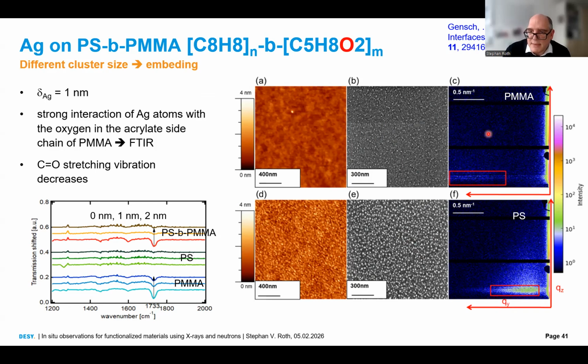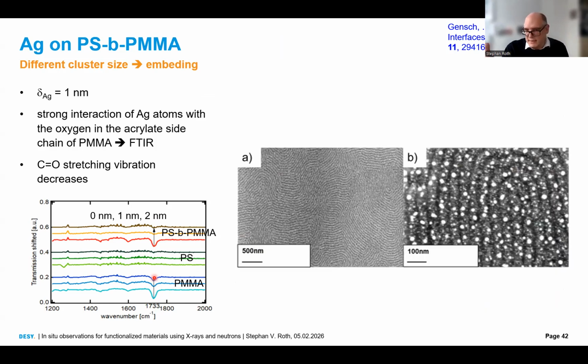You see smaller clusters on PMMA, larger clusters on PS. And if you do FTIR, you see that the CO stretching in the PMMA is reduced, meaning that the silver undergoes a bonding with the oxygen in the PMMA and thereby shadows this CO stretching vibration, indicating that really the growth modes are completely different on PMMA and PS. And again, you see the same here. The bright parts, the bright lines here are polystyrene, the dark lines PMMA, and you see that these silver clusters really selectively grow on top of the polystyrene. This is what we expect also due to FTIR.